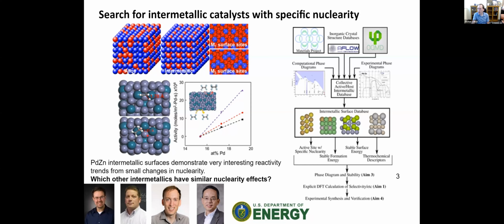And this is really, really interesting because if you're trying to react to C2 on the surface, you can go from a material that doesn't want to interact with this acetylene molecule to one that wants to interact with a C2 intermediate much more strongly. And you get very, very large changes in activity and selectivity.